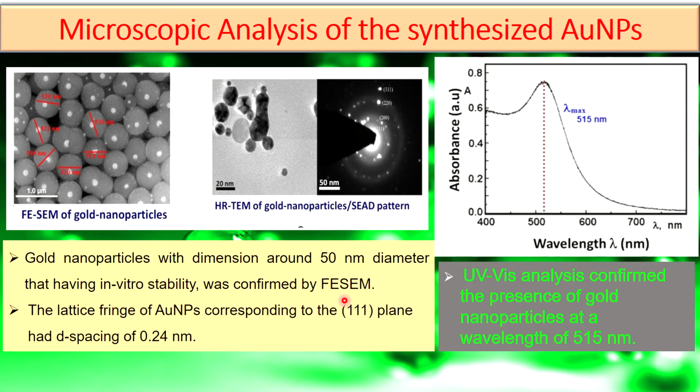These are the microscopic analyses of the synthesized gold nanoparticles. FESEM of the gold nanoparticles shows that the dimension is around 50 nanometers. And the morphology and crystalline nature were confirmed by the HRTEM image. And this shows the UV visible analysis. This shows the presence of gold nanoparticles at a wavelength of 515 nanometers.